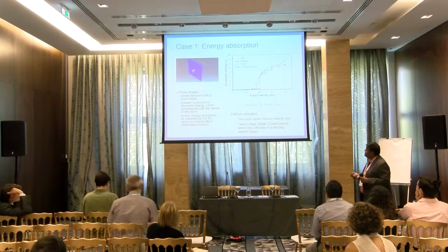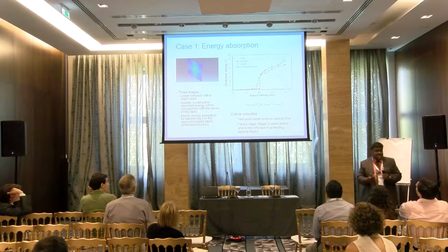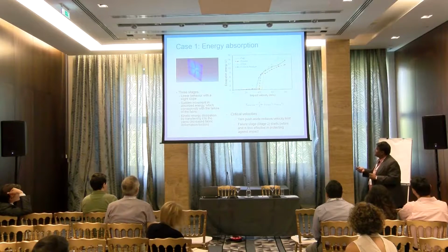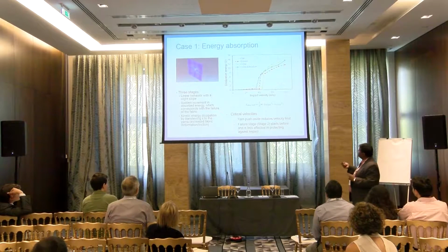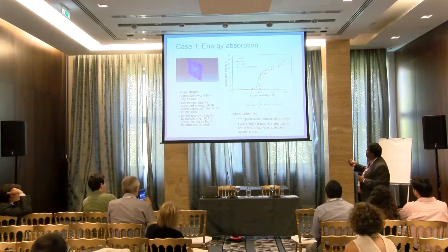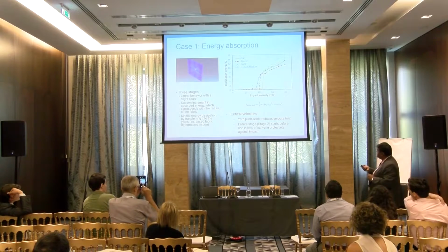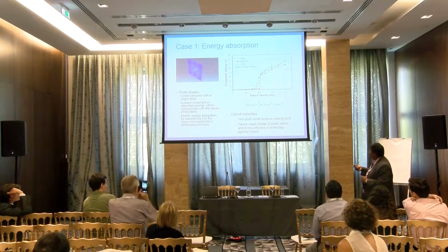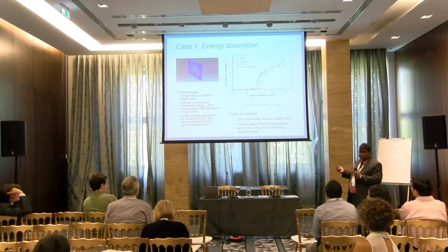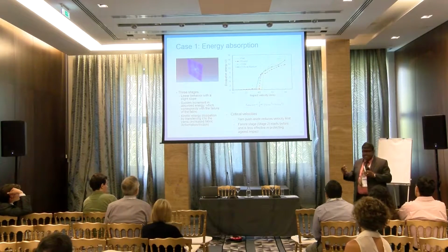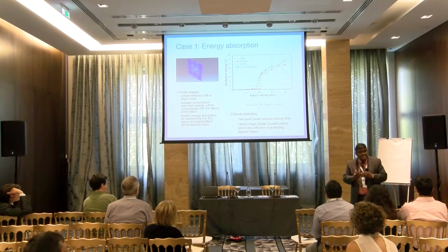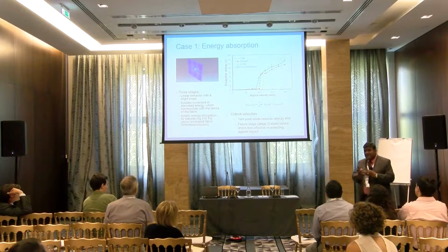So the last thing is we will present some parametric studies of what we looked at, and I'll keep it short, but I think I'm within time. So you can see we conducted this, as I explained, dissipation energy versus impact velocity. We have compared four different projectiles. And for each case, we can see a linear behavior when the projectile rebounds, and there is this degree of energy dissipation, which is the same as energy absorption, due to the fabric damage as well as the friction between the different fibers.